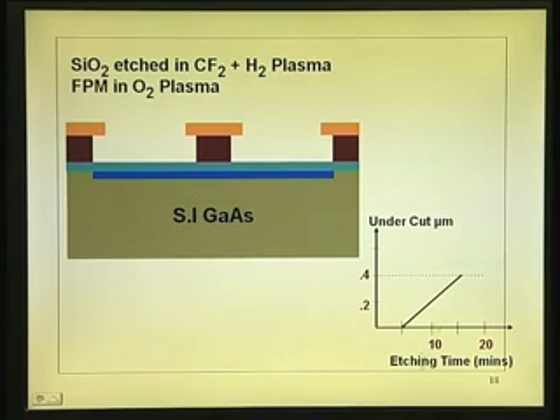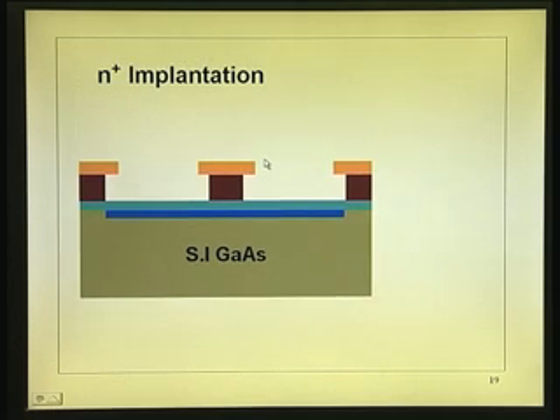In fact, I have shown you a graph here which shows etching time in minutes versus undercut. I can put 10 minutes, you get about 0.2 microns undercut. This is undercut, which will decide the distance between the gate and the drain. Then, now go back to this curve, it is very helpful. This is the one through which you implant here with the metal, but whereas here in this particular case what you are doing is you implant using this mask. See the implantation coming through. So, wherever silicon dioxide is there, implantation does not take place, that is N plus.